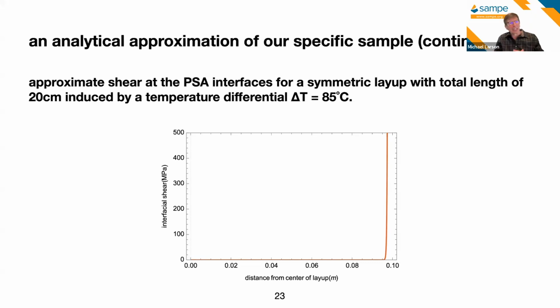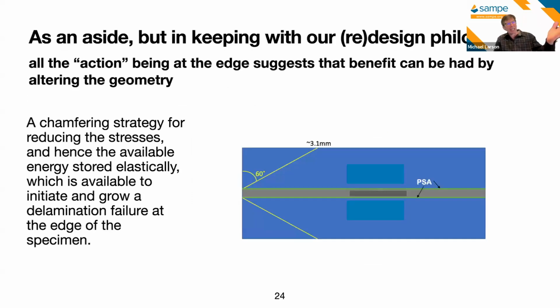of the layup that is intense at that edge, which is why we typically see delaminations proceeding from an edge of these kinds of differential temperature driven failures. And this happens to be just some numbers for a delta T of 85 degrees C, with numbers representing, again, structural plastics that we often want to glue together. So the nice thing is it's intense at the edge, but it's fairly small.